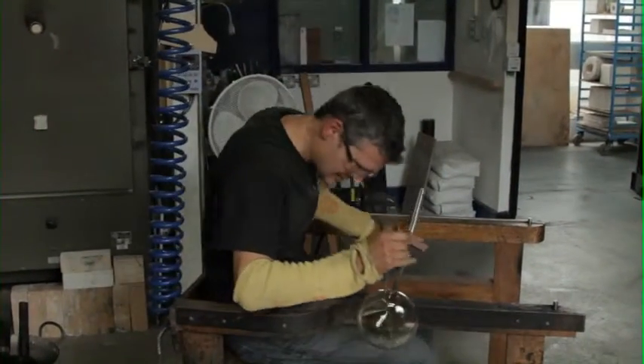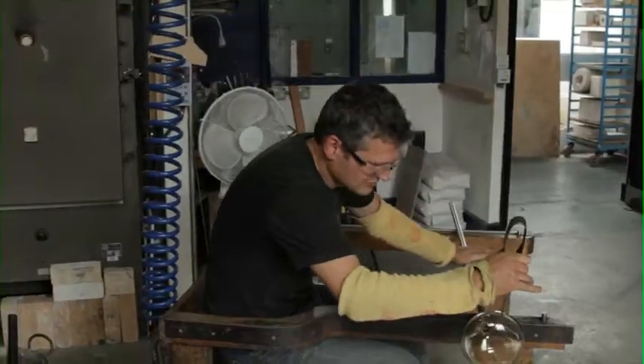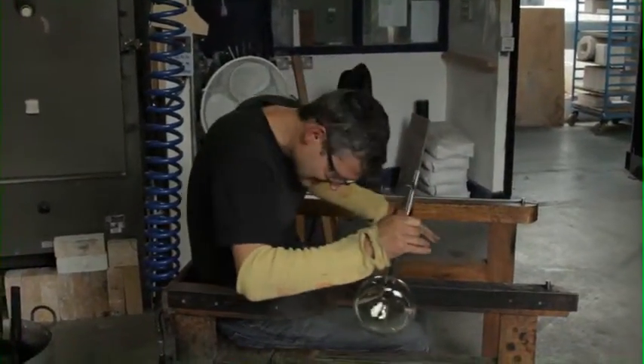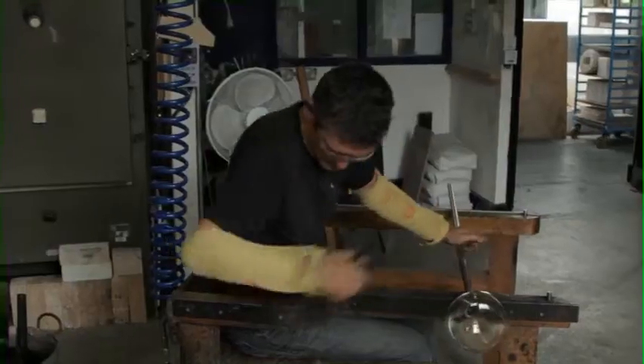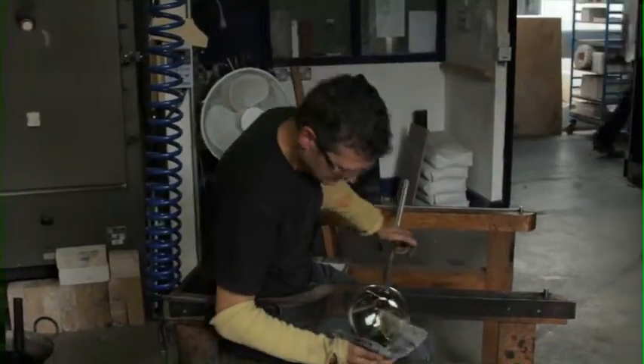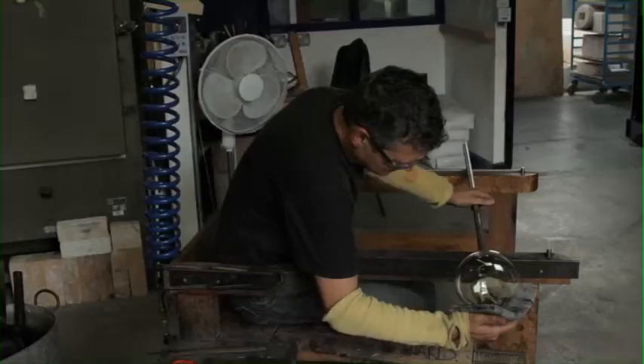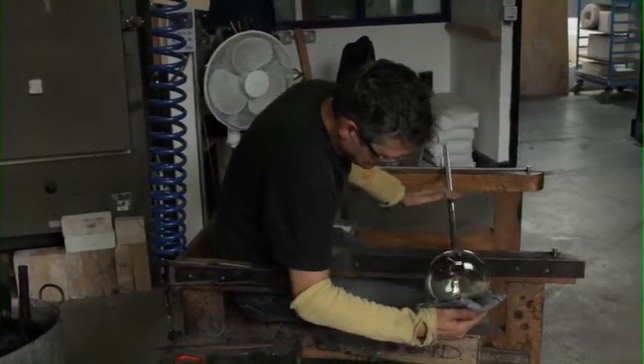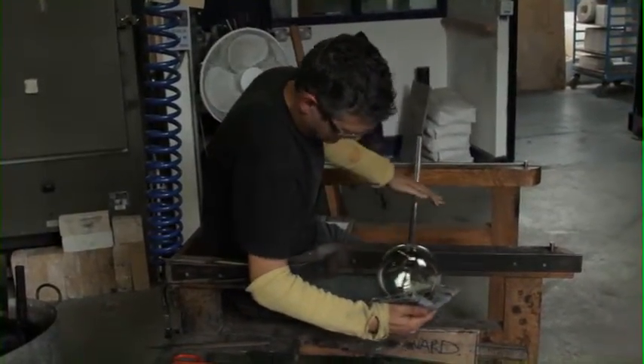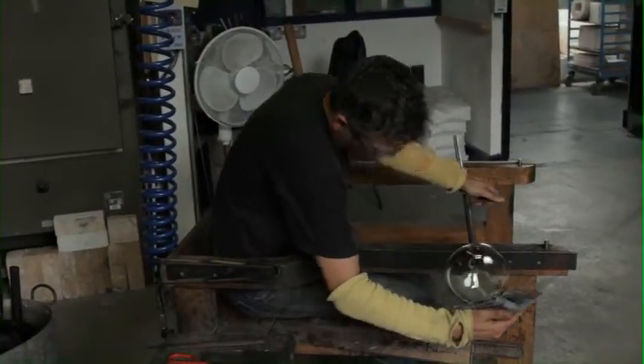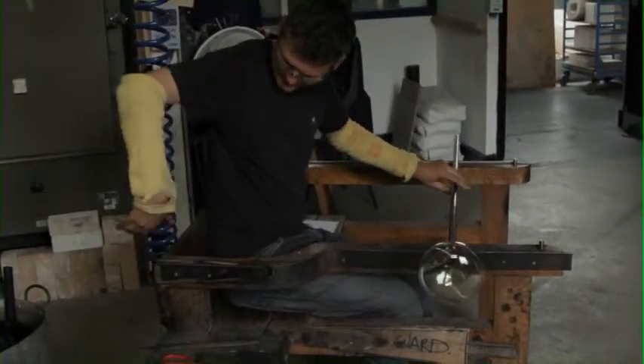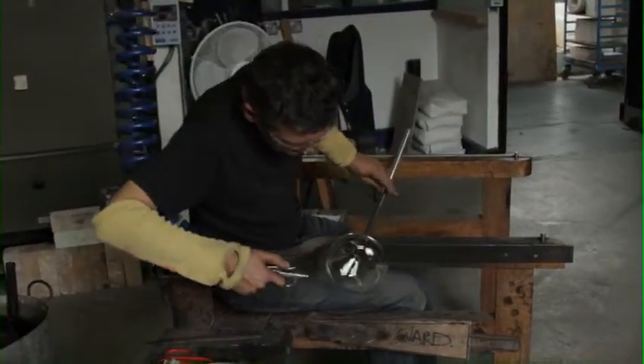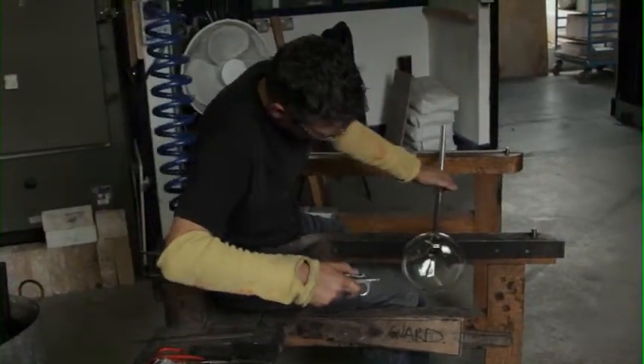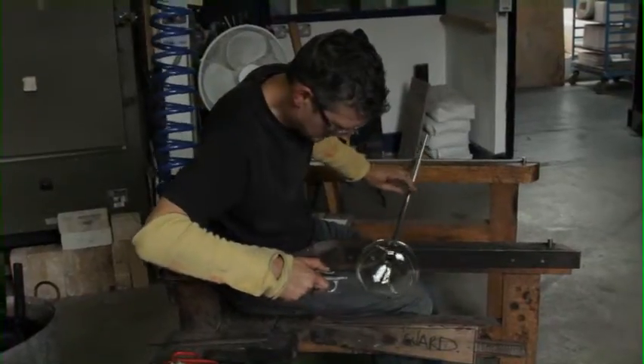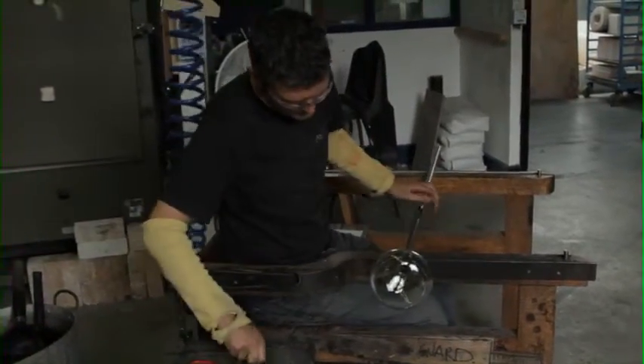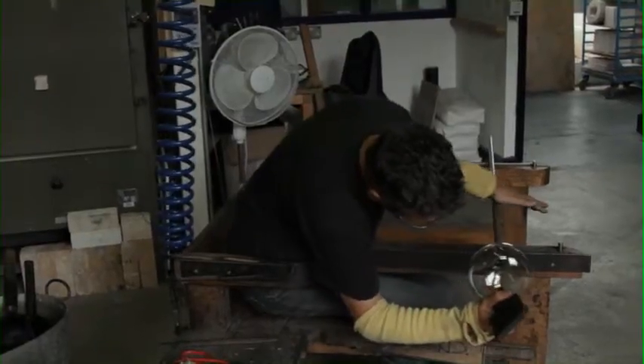In order to put the Venetian glass project in context, I think I should very briefly describe how some of the different glass types I've worked with feel to work. Lead crystal is very soft and long working. If it's over 24% lead, it's an extremely forgiving glass, which is why it's favoured by glassmakers like myself with an art background. We can take more risks with a longer working glass. Its main disadvantage is that it's very heavy when working on large pieces. It can be a third heavier than a leadless glass, depending on the lead content. Objects and rims tend to be rather thick, as the glass quickly melts back when it's reheated. We have to reheat the glass to stop it failing due to thermal shock.